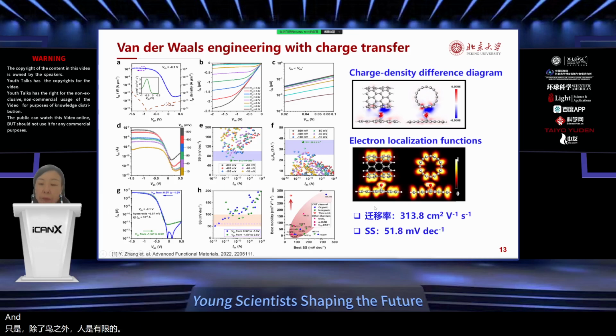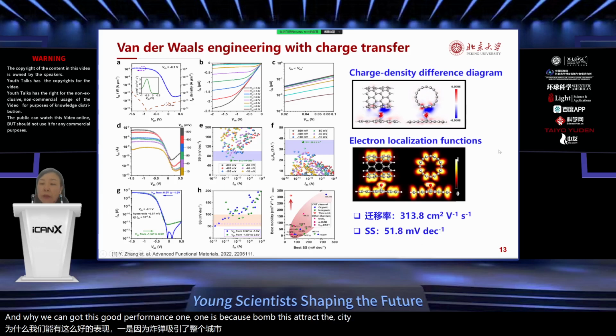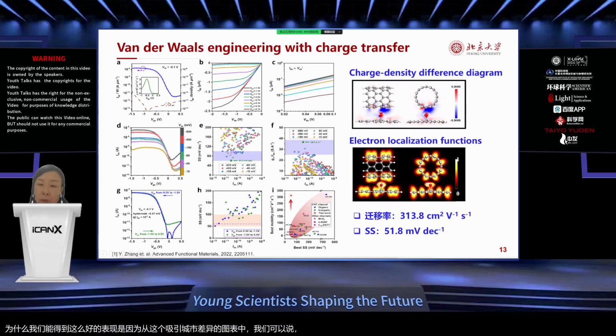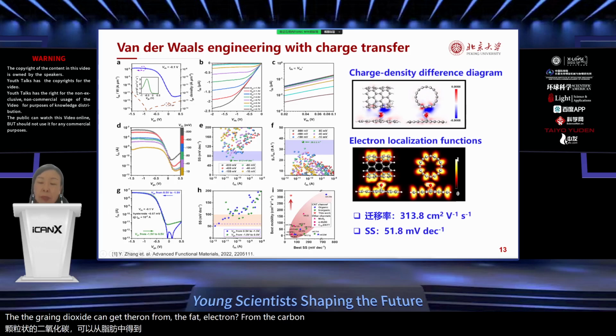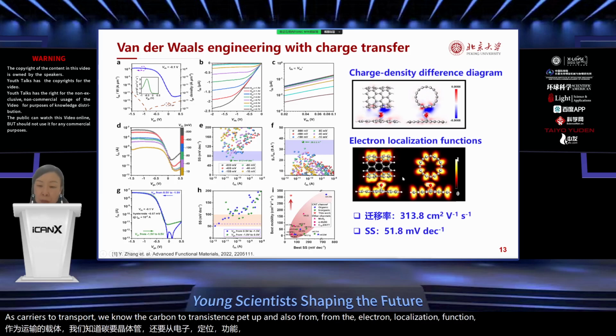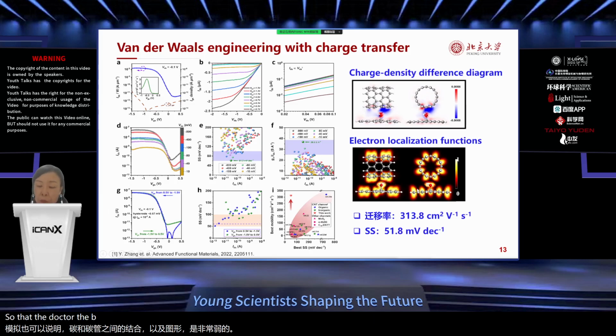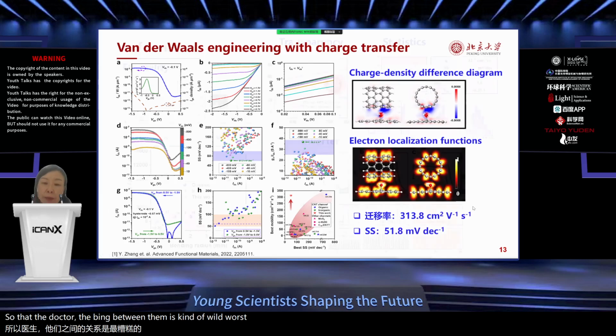And why can we get this good performance? One reason is that from this charge density difference diagram, we can see the graphene oxide can take electrons from the carbon nanotubes and then leave more holes as carriers to transport. We know the carbon nanotube transistor is p-type, and also from the electron localization function simulation, you can see the bonding between the carbon nanotubes and the graphene oxide is very weak, so the bonding between them is kind of a van der Waals contact.